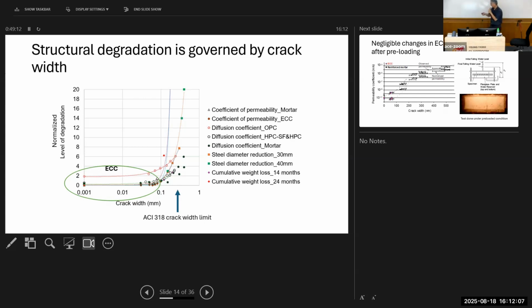Now this plot comes from data that I collected, my students collected, I should say, from the literature. And there are many different sets of data. You can see that there are data related to the permeability measurements, ion diffusivity measurements, corrosion of steel, loss of weight of the steel after corrosion, and so on. So in order to put it on the same chart, I have to normalize it, normalized by the level of degradation at very tiny crack width. Okay, and very interestingly, you see the degradation stays almost flat. All these curves are very flat, doesn't change very much until it gets to a crack width about 0.1 mm, or 100 micron. Above that, you see that the degradation shoots up very fast.